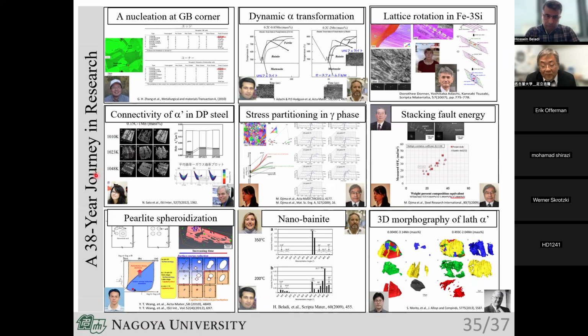And we developed a quantitative method to evaluate the dual phase microstructures, focusing on the ferrite and martensite. This was a key to correlating microstructure with mechanical properties. And here I also learned a lot from Professor Peter Voorhees, Northwestern University, to quantify such kind of three-dimensional microstructures.